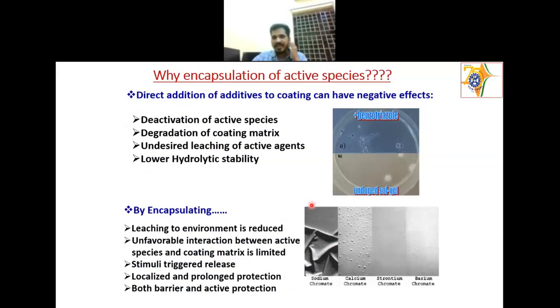This is actually the idea of self-healing in corrosion. And I told you generally two ways you can do that. One is that you can directly add a kind of inhibitor into the coating, and in the image you can see this is an undoped sol-gel coating. This is a doped sol-gel coating. Doped means you added a kind of benzotriazole here. So what is happening when you're directly adding the additives into the coating? We found that the benzotriazole will have some negative effect on the barrier property of the matrix itself. So it is degrading the barrier property itself.